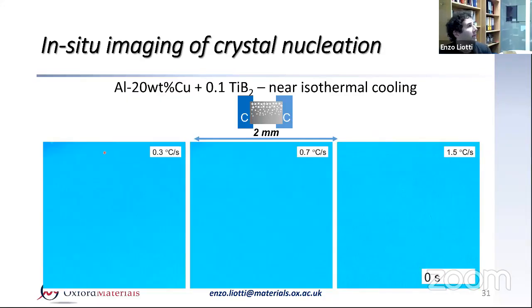So here is an example of nucleation of aluminum alloy from the liquid. What I'm going to show you is three video sequences of the solidification of an aluminum 20% copper alloy, which was grain refined with TiB2. The difference in the three videos is just the cooling rate. From the left it is 0.3, and the one on the right goes up to 1.5 degrees a second, right? And these were solidified near isothermally, with the two heaters kept at the same temperature, and grow horizontally.